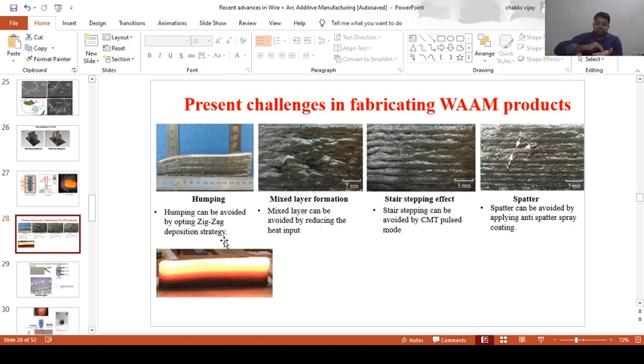For example, zigzag means the first layer will be deposited, after that the second layer will be deposited just like this, so there won't be any continuous deposition taking place. In a zigzag manner we deposit, and if we deposit that way, this kind of humping can be greatly avoided. Even we could see this kind of mixed layer formation, where we couldn't identify which layer it corresponds to. All the layers are sandwiched and it looks clumsy.